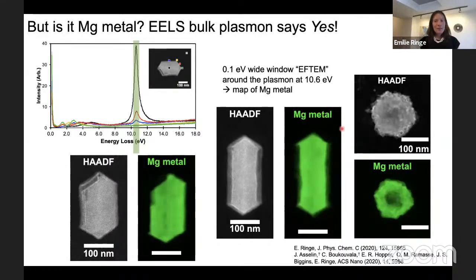Another way to check that this is still magnesium metal is to do what's called a bulk plasmon map. Magnesium and aluminum are unique in that they have a very sharp bulk plasmon absorption in the 10 to 15 eV region. So we can map that with EELS, and it tells us this is metallic magnesium. Most metals have a bulk plasmon, but for aluminum and magnesium they're very sharp and easy to see. It's very convenient, and we can map exactly where the metal is, look at our EDS maps, and really understand what the shape of our plasmonic structure is. We have a number of projects now doing tomography with these maps to get the real shape of the magnesium metal. We're pretty excited about that.